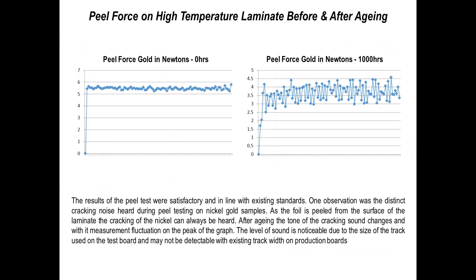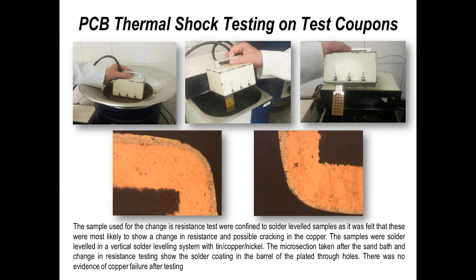This graph illustrates the changes in force measurement. An interesting thing that happened is that when you expose large nickel gold boards to high temperatures for a long period of time, you also start to have an impact on the nickel — you can actually hear it cracking during the peel testing. We did thermal shock testing also on the printed circuit boards to make sure they would stand up to high temperatures.